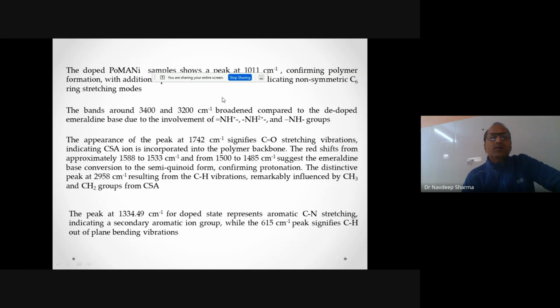That confirms that our CSA dopant is attached at the ortho-methyl positions of the conducting polymer. The bands around 3400 and 3200 wavenumbers are broadened compared to the de-doped emeraldine base, which shows the involvement of amine, imine and NH groups, and gives the confirmation that in the doped state the dopant material is properly attached at the ortho positions as compared to the de-doped state.